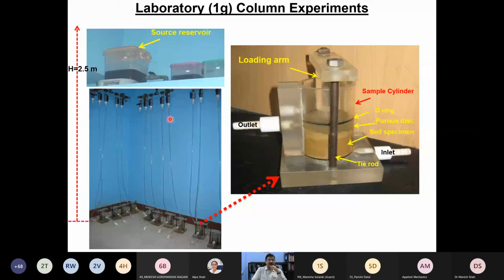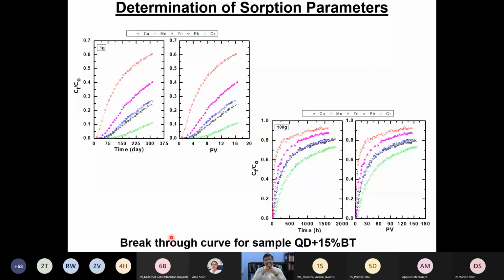If you look at it, the inlet tube I connected at the bottom, and I allowed the contaminant to flow in the upward direction because we want to avoid any kind of sidewall leakage. The outlet is collected using a small tiny bottle here, and the effluent is analyzed for the concentration over a period of time. For example, in a 1G environment, this is the effluent concentration with respect to time. Please note that we have measured different varieties in the case of soil, but in the case of a geomembrane, we have again measured for organic contaminants.